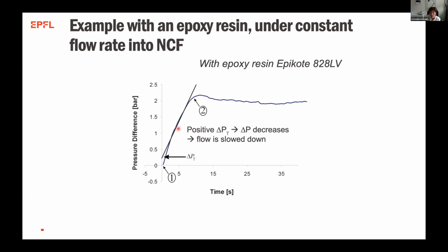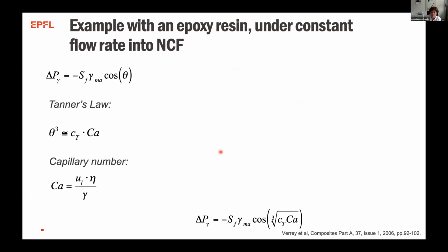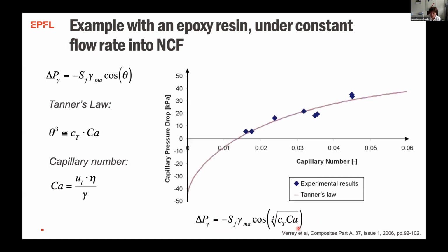You have a constant increase of the pressure, and then the constant increase of the pressure, of course, starts from zero because we are doing a real experiment. But if you take the slope and you extrapolate, the slope extrapolates to a certain value, which would be your delta P gamma measured for this value of capillary pressure drop. And then, knowing Tanner's law, if you increase the capillary number, your delta P gamma should increase following this equation. And it kind of works.